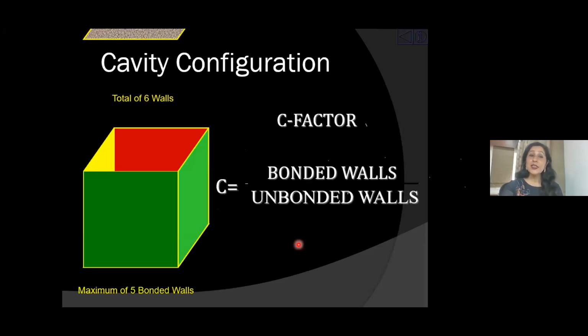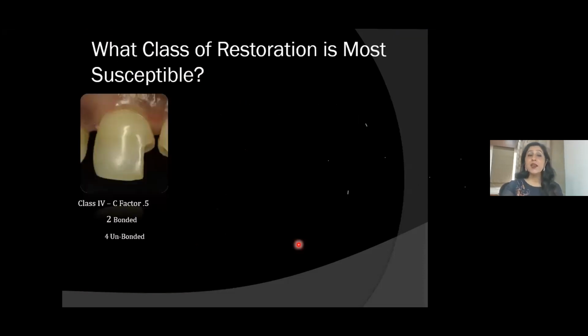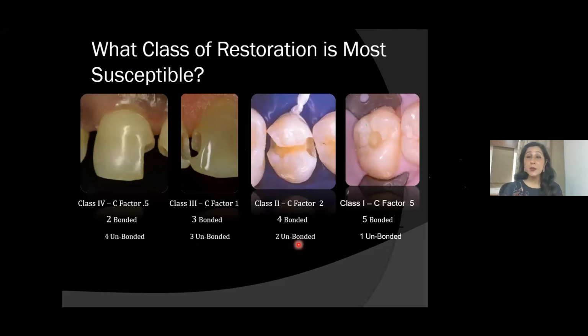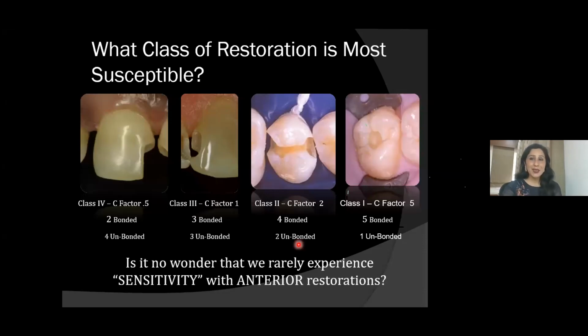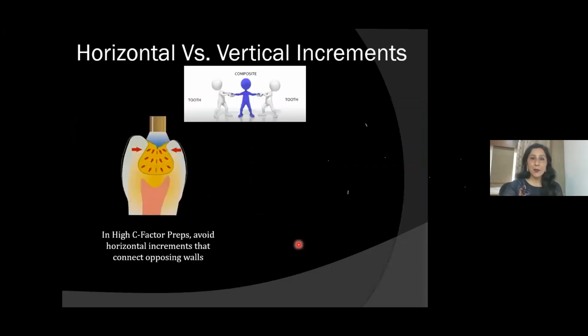So what is a C factor? C factor, my dear friends, is a ratio of bonded to unbonded walls. Tell me, in which class of restorations will you have the maximum C factor? That is class 1, because there are 5 bonded walls and 1 unbonded. Whereas you hardly see any post-operative sensitivity in your anterior restorations, the class 4, because the C factor is only 0.5, because there's a lot of free surface area for the composite to release its stresses. And so the same concept is introduced in this anatomic placement.